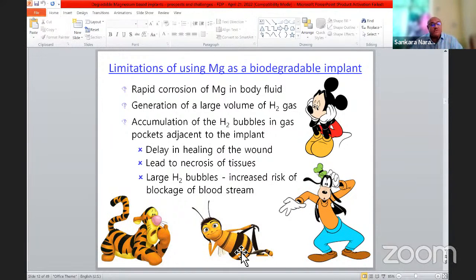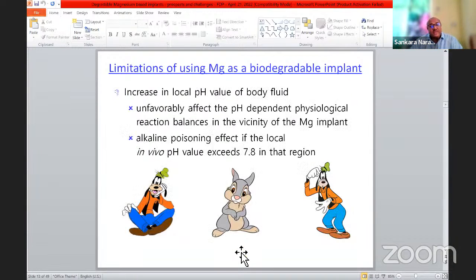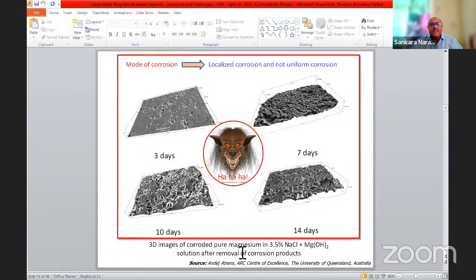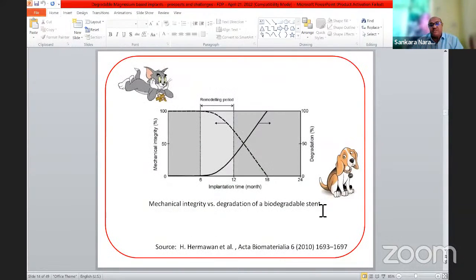So we need to control the rate of the evolution and corrosion. And there will be an increase in the local pH that will affect the physiological balance. Those things are there. The problem is iron undergoes uniform corrosion. It removes layer by layer. But magnesium undergoes pitting corrosion. You see that pitting corrosion. So it drills deep. So it's very, very bad. We cannot change the mechanism from localized to uniform corrosion. So that is the problem. And since it undergoes pitting corrosion, it undermines the mechanical integrity of the material. So that is the major problem with magnesium.